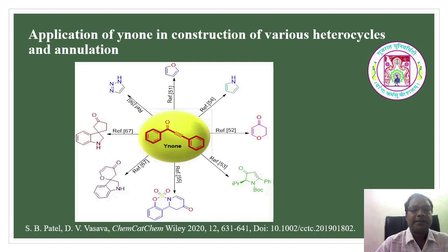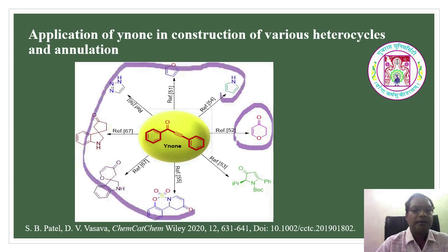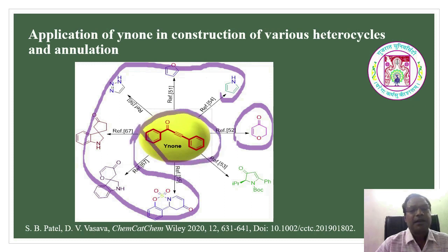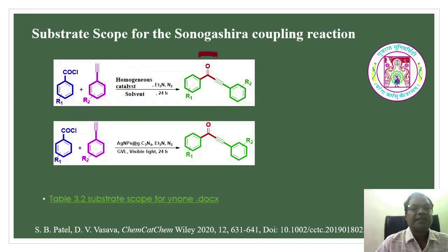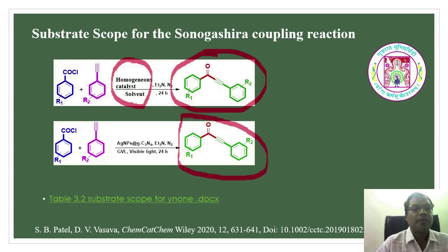utilized to synthesize the different heterocycles. So in the literature all these heterocycles are reported from the Ynone. So we have reported this Ynone by using the Ag nanoparticles. To synthesize the Ynone, homogeneous catalyst is utilized in the literature. Now we have reported the synthesis of Ynone by using the Ag nanoparticles doped on the carbon nitride by